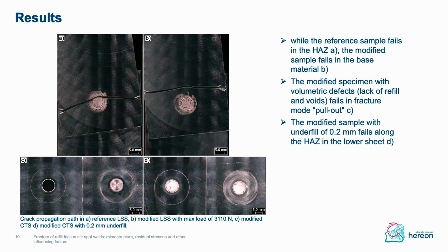Below you see the cross-tension samples, while this one is the one without the 0.2 millimeter underfill, where we have a classic pull-out of the spot weld. And this is the one where we have the underfill, where the crack propagates along the heat-affected zone.